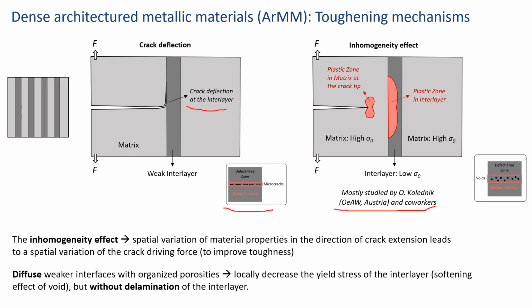However, in much of the work which has been done on architectured materials in metals, this was not easy to study because most of the time you would have issues in architectured metals happening at the interface. But in our case, since we are using a diffuse interface which contains porosities but no interface per se, we can hope to avoid any issues with too massive crack deflection.